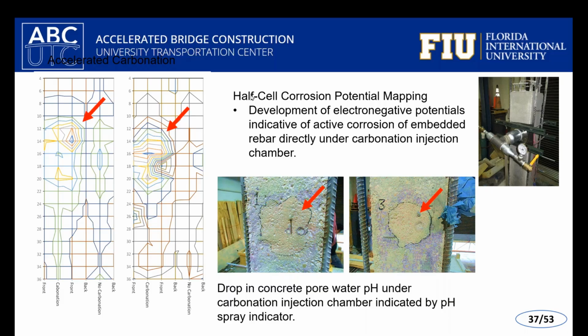Essentially, the oblong circles, or the more elliptical shape you have in the middle, is the interior portion of that pressure vessel, where the flange is connected. After the accelerated carbonation, we remove the system and spray the phenolphthalein pH indicator on the surface. Pink is showing where it's not carbonated, and the not-pink color is where it is carbonated. So we're fairly happy with how effective that technique was to choose a localized location of carbonation. The arrows are pointing to that center part in the middle of that pressure vessel where the concrete was carbonated. So we verified as well for the embedded reinforcing steel, the longitudinal steel that was placed for the retrofit purpose for the project that Fatima mentioned before.